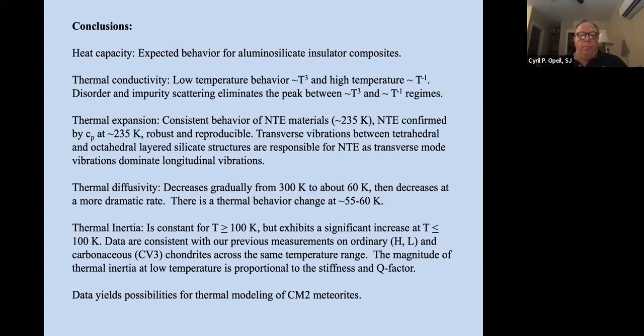Thermal diffusivity shows a gradual decrease from 300 to about 60, and then the decrease is more dramatic, and that behavior changes at about 55 Kelvin. Thermal inertia is constant above 100 or so, but exhibits a significant increase as we go below 100 Kelvin.